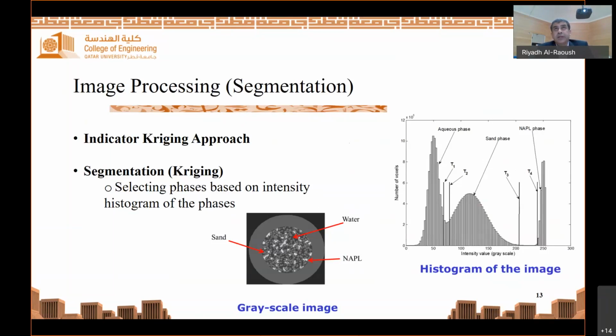The segmentation is done based on the 2-point correlation function. For example, values below T1 are assigned to one phase, values between T2 and T3 are assigned to another phase, and values above T4 are assigned to a 3rd phase. The uncertainty here is between T1 and T2 and between T3 and T4. In this case, we use the 2-point probability correlation function to identify the phase.